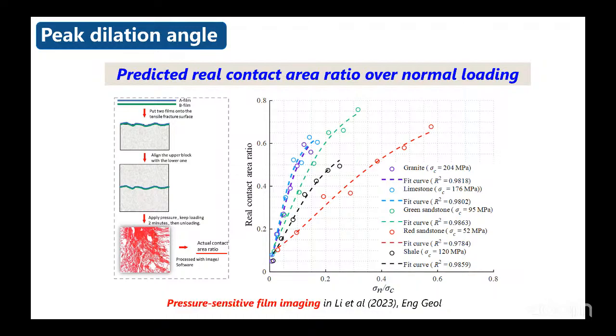To validate the formulation to predict the real contact area ratio, we compared our theoretical predictions to experimental measurements conducted by our co-author, who used the pressure-sensitive film to image the contact zone and associated area under compressive normal loading. From the correlations, we can see that our theoretical work achieved very high accuracy. For details, the audience can refer to the publications in 2023.